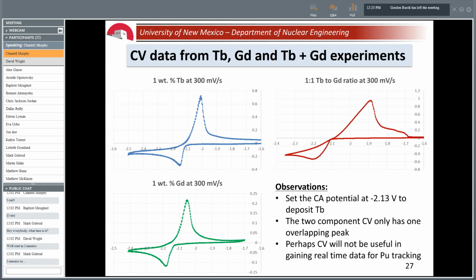The first step was to take CV measurements of a mixture of just terbium. I used 1 weight % terbium in a crucible with lithium chloride-potassium chloride eutectic salt, a total of 50 grams. And this is the CV that resulted, in order to see where my reduction potential starts for terbium. I did the same thing with a mixture of only gadolinium. Then the experiments themselves were a mixture of terbium and gadolinium. It was expected that in the 2-component system there would be 2 reduction peaks, but there's only 1, and that was an interesting result.